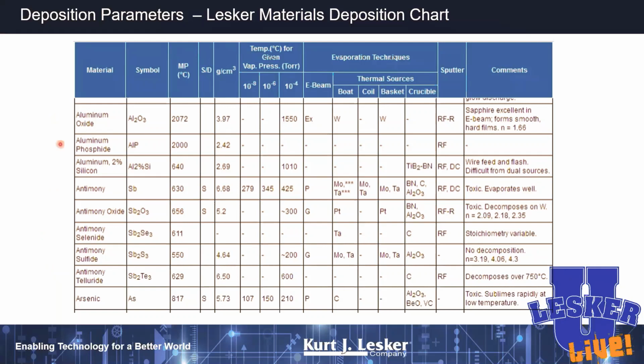If we look at aluminum oxide as an example here, we're giving you the chemical formula, the melting temperature, and the theoretical density, which you're going to need for a calculation I'm going to show you in a second. And we're saying for thermal evaporation, if you want an equilibrium vapor pressure of 10 to the minus 4 torr, you need to heat aluminum oxide up to 1550 C. Boom. There's your answer for that.